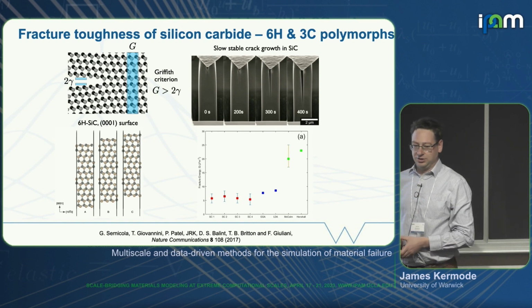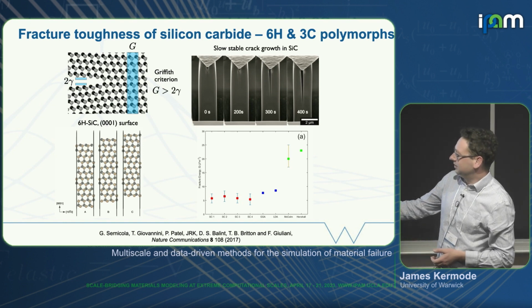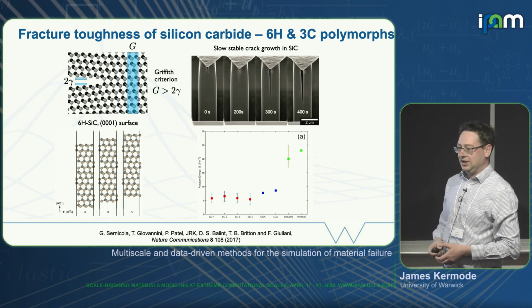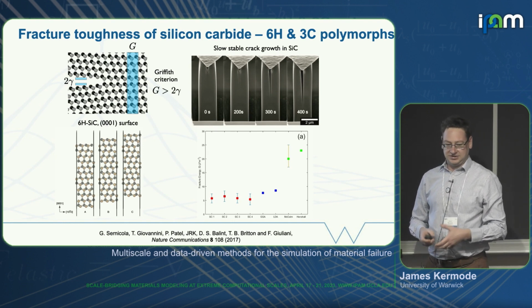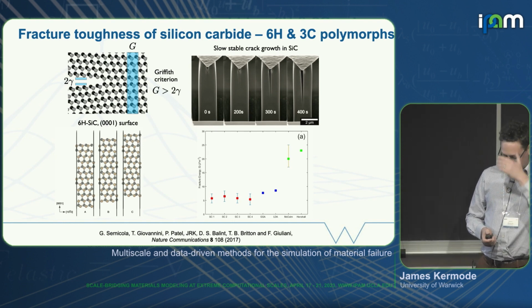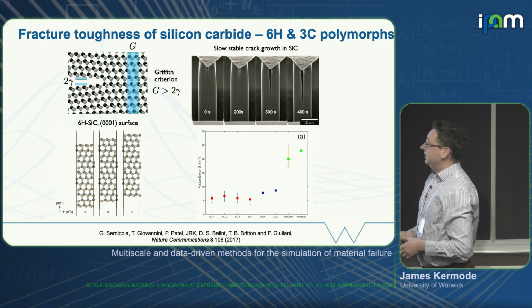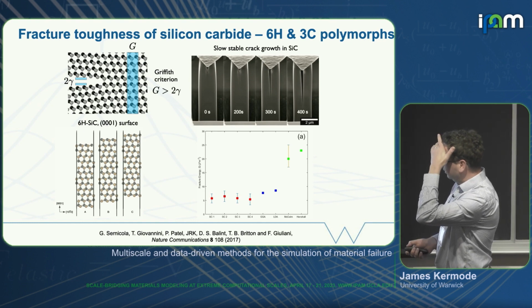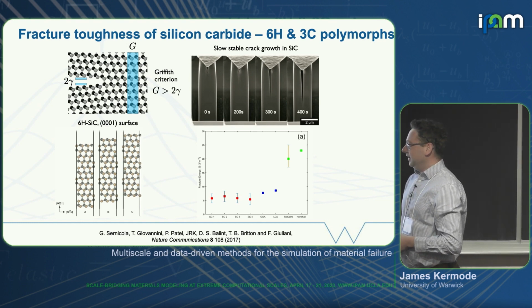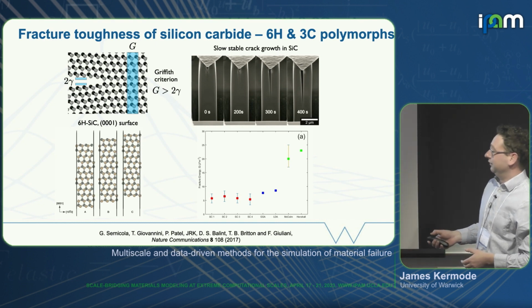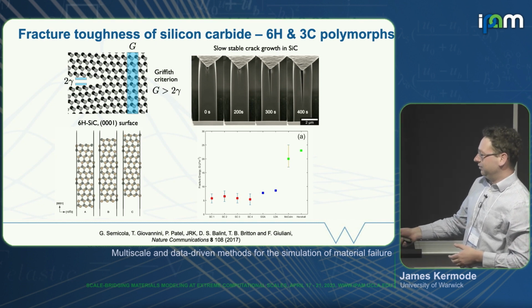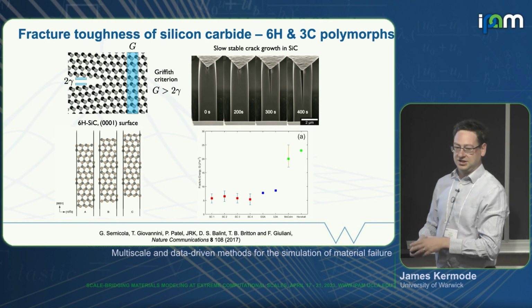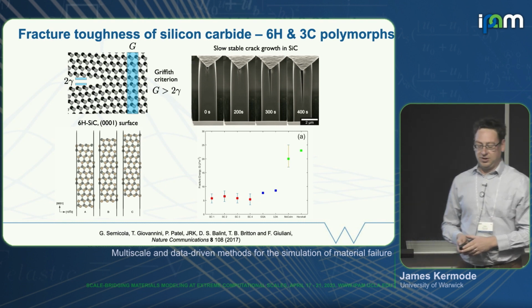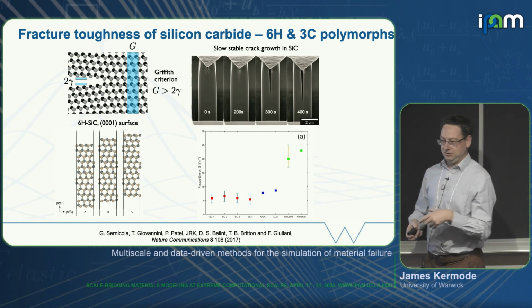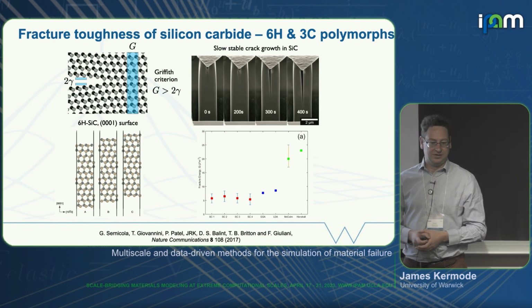So we can use a kind of scale bridging type approach to directly compute the cost of creating those surfaces and then use the thermodynamic energy balance to say that that's the energy that corresponds to fracture. We did this in silicon carbide a few years ago, and we had to take account of the local chemistry in that there are different polymorphs of silicon carbide, different possible surface terminations, and you need to kind of take all those things into account. But that's all possible within the couple of hundred atoms that you can fit into a density functional theory calculation.